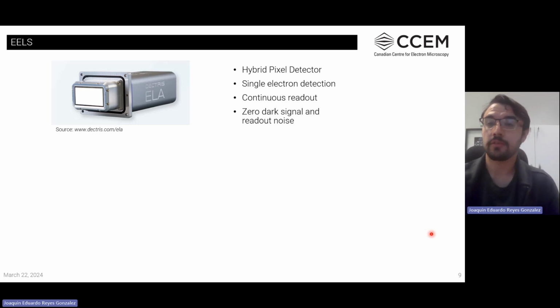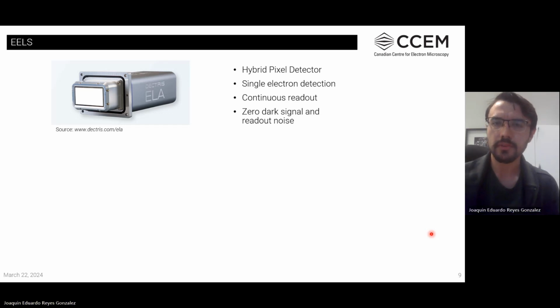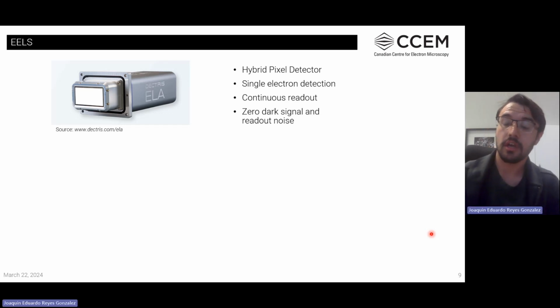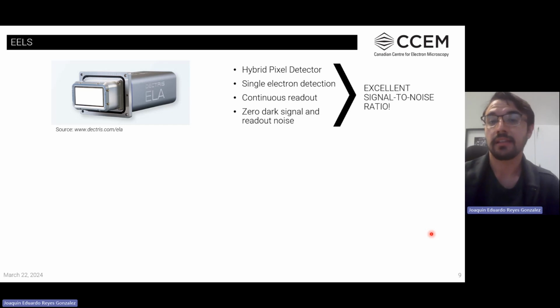Dectris ELA is a hybrid pixel detector made of a set of 8 silicon chips capable of collecting single electrons with continuous readout. This is optimized for EELS, and the purpose of having single electron detection with continuous readout is to maximize the efficiency of collection when we're doing our experiments. Additionally, the system has zero dark signal and zero readout noise, which eliminates a lot of the noise coming from the instrument or detector when doing measurements. All these characteristics allow for an excellent signal-to-noise ratio on the data, even at fast acquisitions.